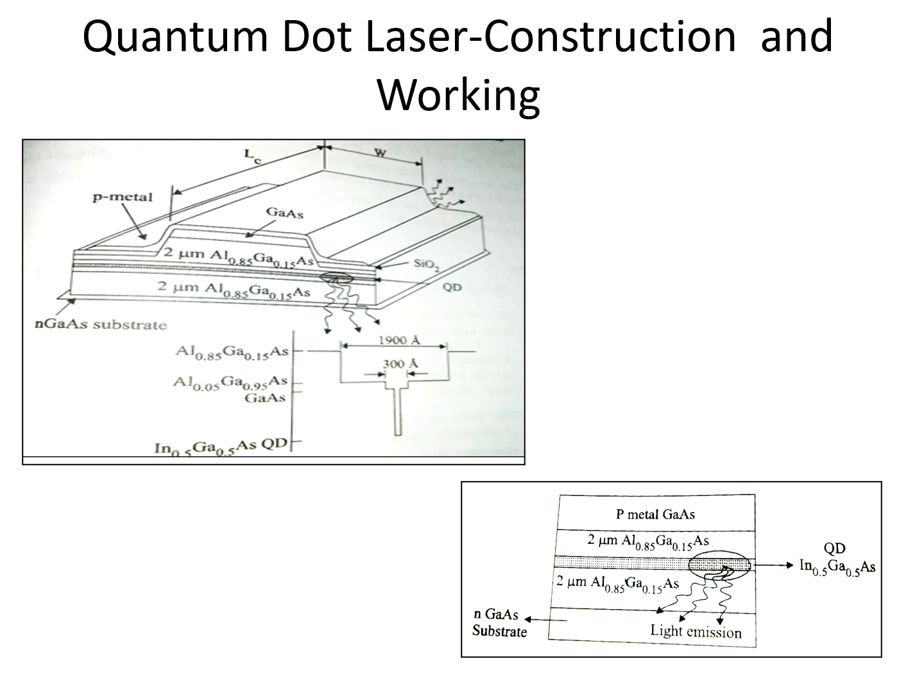Normally quantum dots are made up of InGaAs, that is In and Ga taken 50% each along with As. Then above and below you can see AlGaAs, that is Al 0.85 Ga 0.15 along with arsenide.